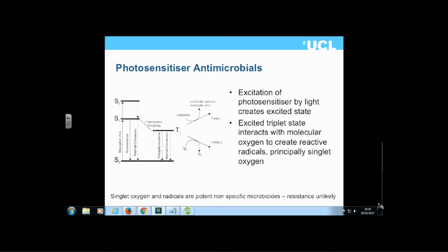We've also shown in some systems that we can actually remove existing biofilm. If a biofilm has formed on these surfaces and you shine light on it, we're able to destroy the microbial surface. The way light interacts with dyes to generate antimicrobial species, in our case, can go via a type 1 or a type 2 mechanism.